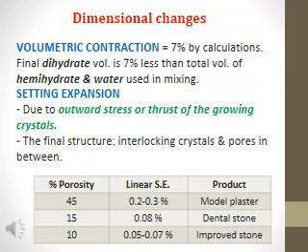Actually, when the material sets, it undergoes expansion due to outward stress or thrusting of growing crystals. During their growth, the crystals push against each other in an outward direction, so the expansion occurs during setting, and the final structure that results is interlocking crystals and pores in between these crystals that are filled with water, and this water evaporates by time.